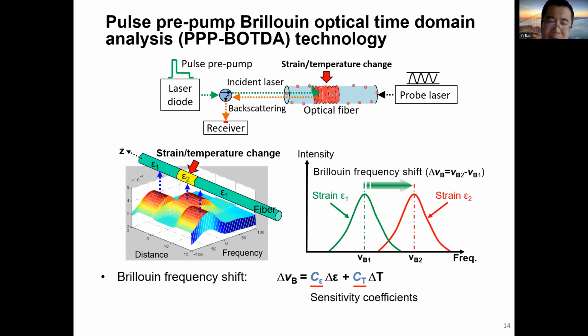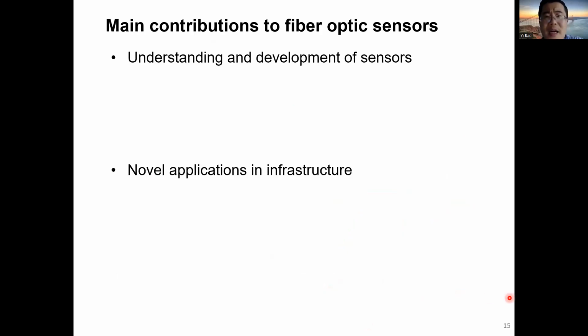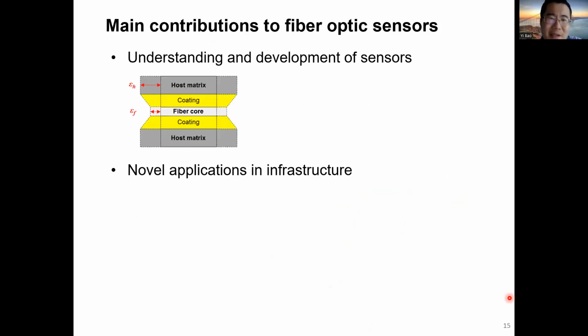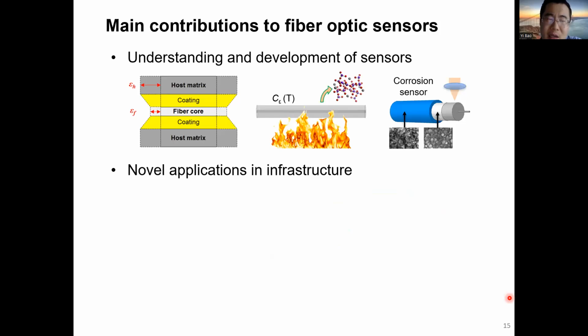And at normal temperature, this frequency shift can be related to the strain change and temperature change using a linear equation. This equation could be applied when the temperature change is small. So it's a linear equation, very simple, and we can calibrate the sensitivity coefficients in this equation. Well, the concept is pretty straightforward. And how about our research? We have made some contributions to the basic understanding of distributed sensors, including the strain transfer behavior, high temperature sensing, and corrosion sensors.